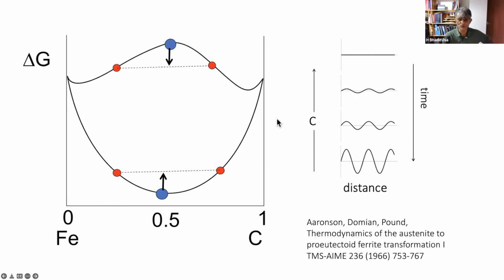It will grow. So you start off with a homogeneous solution, and you get a composition wave which grows in amplitude. So you need a specific set of thermodynamic functions for the solution for spinodal decomposition to be possible. And Aaronson and co-workers proved that austenite does not have this kind of a free energy function.